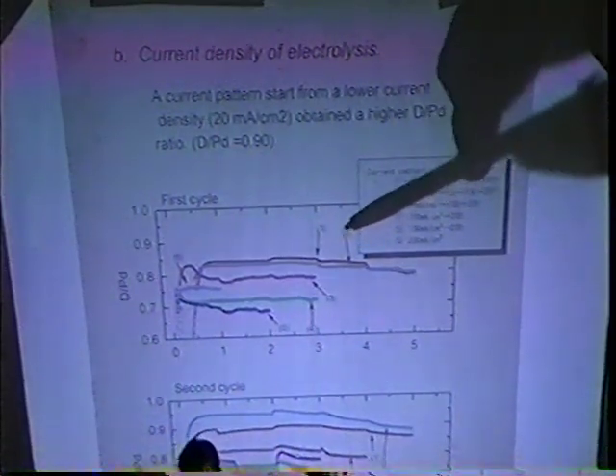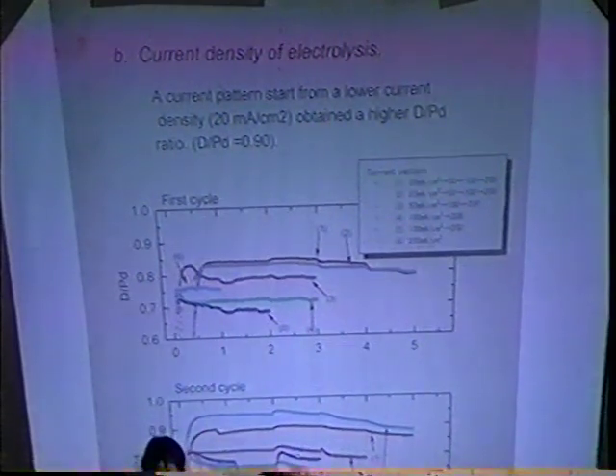This figure illustrates the effect of changing the current density stepwise. The result suggests that there is an advantage in starting at a low current density initially, and then ramping to higher current density. For example, current profiles which start from 20 milliamperes per centimeter squared, number 1 and 2, give a higher D/Pd ratio than the current profile which starts at 200 milliamperes per centimeter squared, number 6. In the second cycle this tendency is more clear.